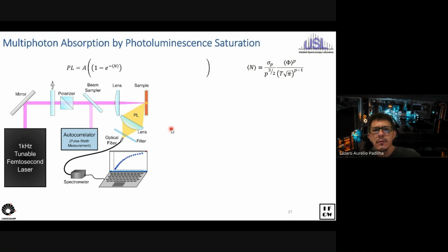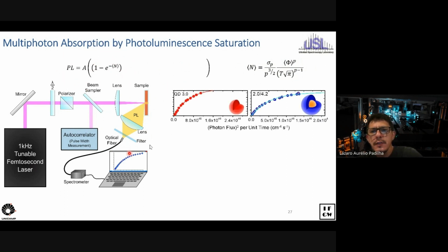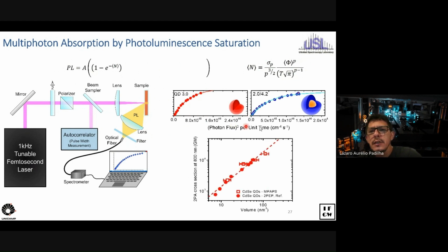parameters. So especially if you have, for example, materials with very weak photoluminescence for the multi-excitons, this reduces to this. And if you take these curves, the saturation curve, and fit, that's basically what we have. So here we have done it for different types of materials. Here is for core only, this is for core shell. And if you compare our data for the core only with the data in the literature, we see very good agreement, showing that this very simple technique is very powerful.